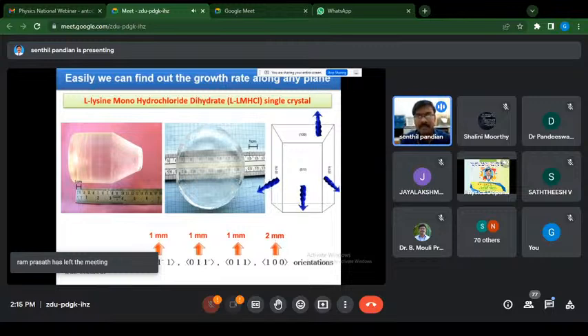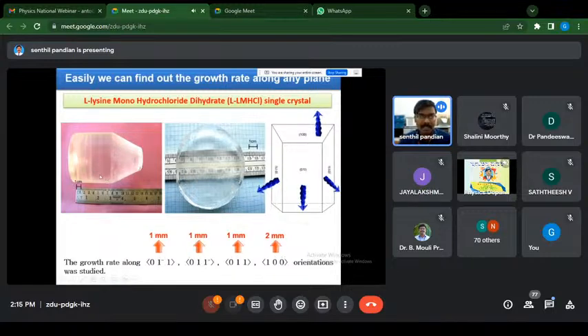Easily we can find out the growth rate along any plane. This is the lysine monohydrochloride dihydrate single crystal grown by the SR method. If you wish to identify the growth rate along different directions, you have to cut the crystal under identical conditions: identical seed crystal thickness, identical glass ampoule inner and outer diameter, identical saturated solution, and identical temperature at the top and bottom portions. You have to measure the growth rate along different planes for any case.